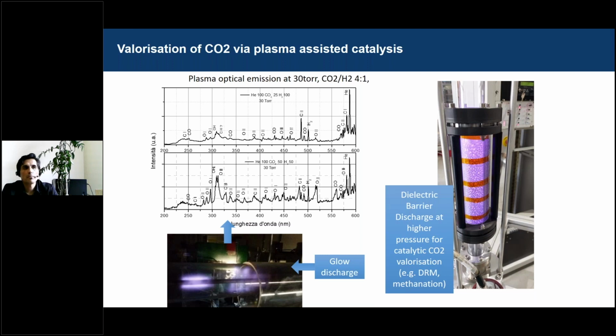because Zecomix is a wider infrastructure. In particular, here you can see the use of cold plasma for converting CO2 into CO and oxygen. This is a very promising technology. These are the last results we obtained in our facilities. The idea is to use a catalyst assisted by plasma in order to split the CO2 into CO and oxygen at lower temperature.